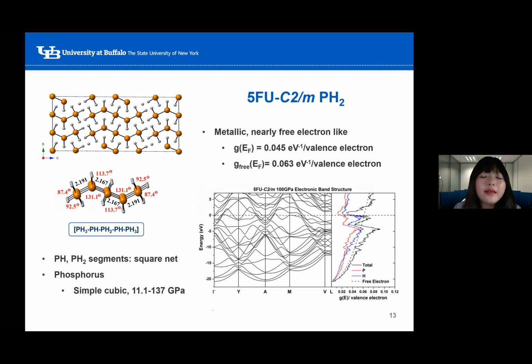So at 100 GPa, the most stable structure is the 5 formula unit C2/m. This structure is comprised of oligomers, and the structure is shown here. The oligomers extend along the c direction, and it's one-dimensional periodic along the a direction. The phosphorus atoms within the PH and PH₂ segments of the oligomers form a square net, which is not uncommon. It has been seen in simple cubic phosphorus, which is the stable phosphorus phase in the pressure range from 11.1 to 137 GPa. And this structure is metallic at 100 GPa, and it is nearly free electron-like.